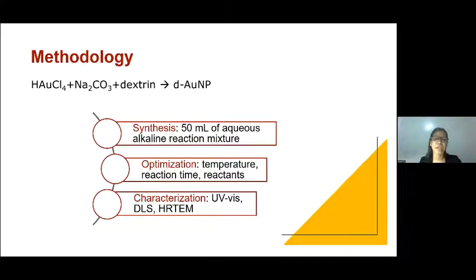All syntheses were carried out such that the total volume of all the reactants, such as the chloroauric acid, 10% sodium carbonate, and dextrin solution, is equal to 50 ml. The effect of temperature, reaction time, and each of the reactants were determined to establish optimized reaction conditions. UV spectroscopy, dynamic light scattering, and high-resolution transmission electron microscopy were used to characterize the morphology, stability, polydispersity, and size of the gold nanoparticles. All laboratory work was done at the Nanobiosensors Lab of Michigan State University, and HRTEM and TEM were done at the Center for Advanced Microscopy at Michigan State University.